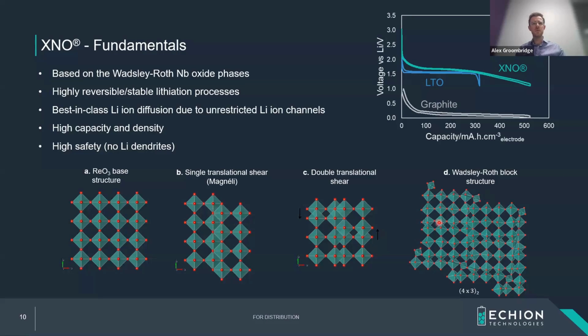And in a simple way, what this means is you end up with structures on the right. This is an example where it's not as perfect as on the left, octahedral matrix. We have something that's more held in place by these shear structures of edges and corners where we have these oxygen sharing. And what this means is when we want to put lithium ions into it, it's an intercalation approach, lithium ions will flow very easily through these spaces which you can see between these octahedra without limitation. Some of the best-in-class lithium-ion diffusion comes from these materials, way above those of lithium titanate. It's a very constricted pathway coming through. It's also a very stable, reversible process because we have these shear edges locking everything in place. You can't expand and break apart the structure going through.